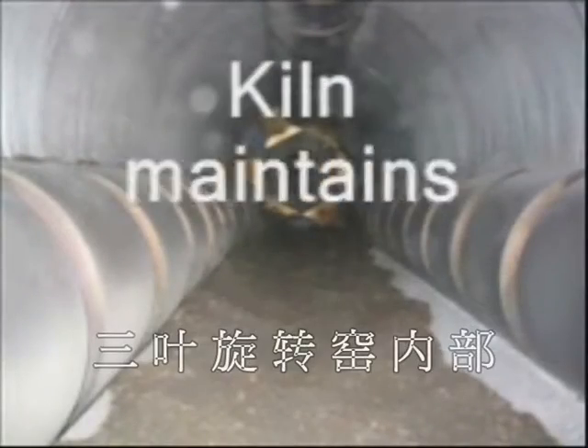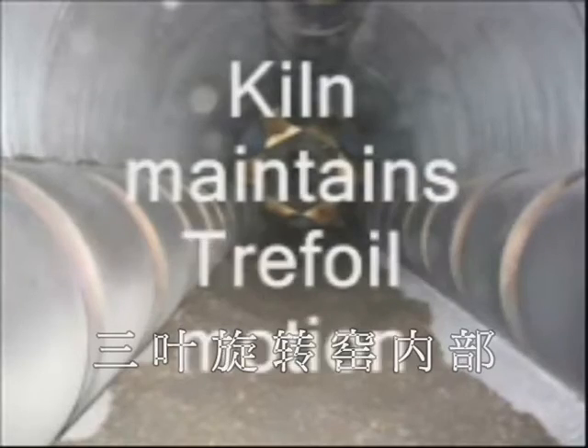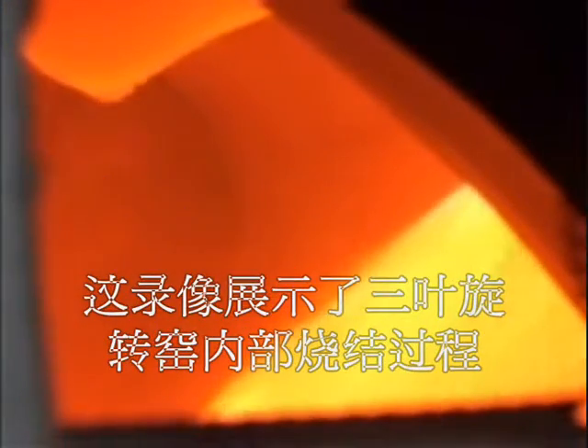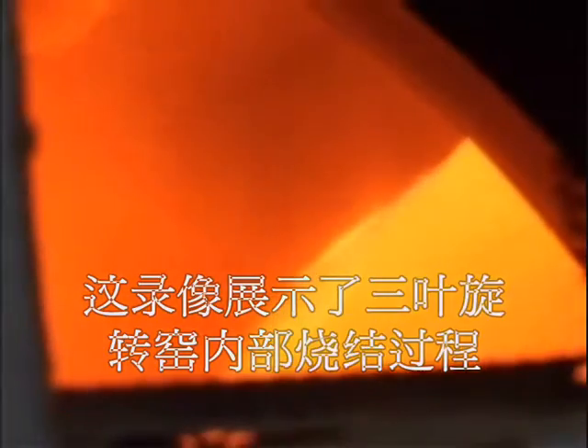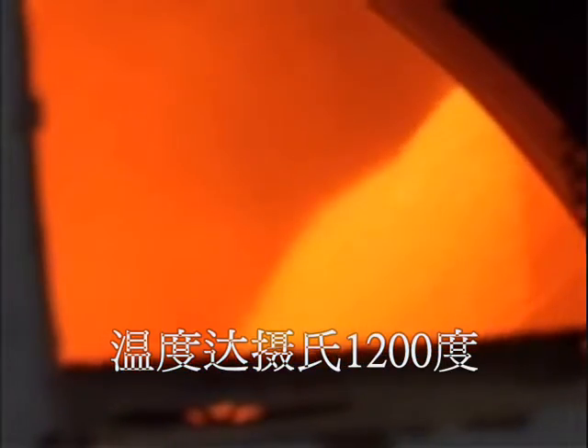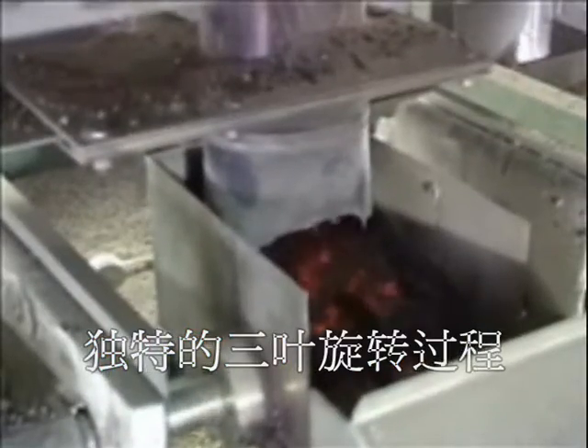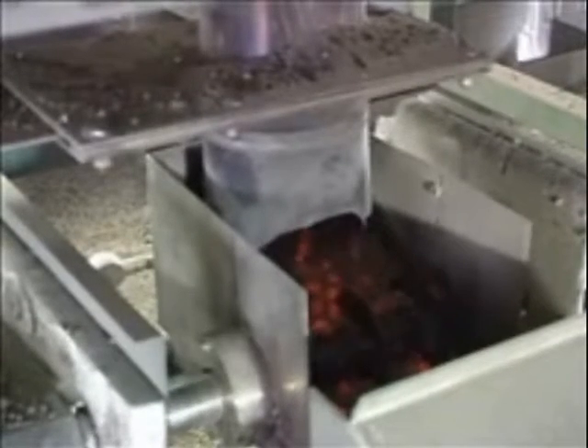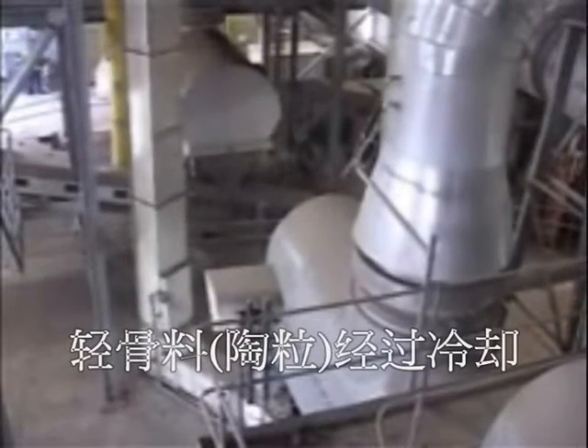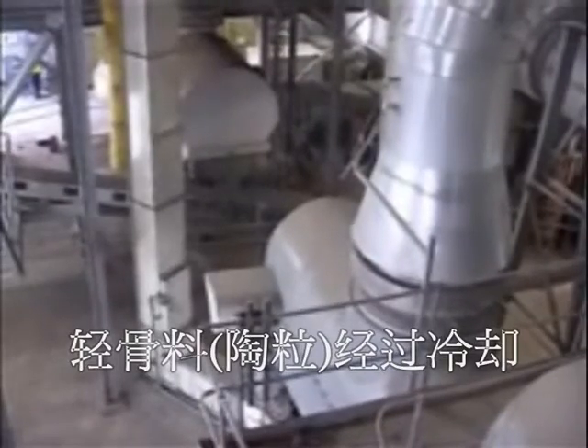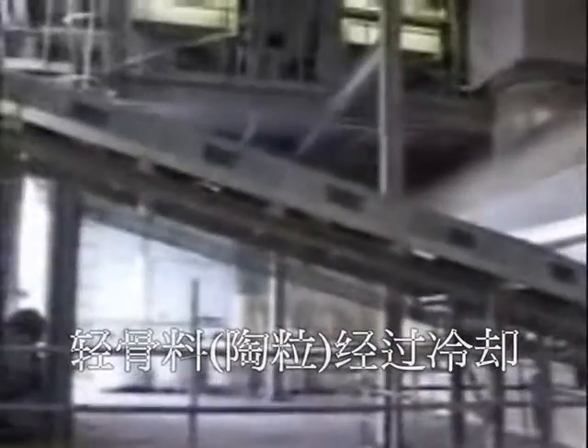The internals of which still maintain the essential trefoil profile. The pellets are fired at a temperature of close to 1200 degrees C before exiting via combustion air preheater and then a fluid bed cooler before the material is taken to stockpile.